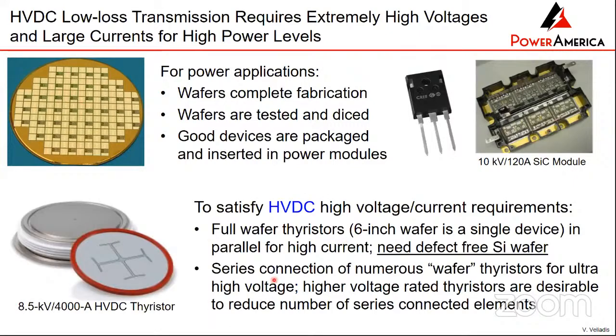And that's what is being done for silicon carbide. However, if you look at silicon, because it's such a good material and the whole wafer is defect-free, they can make a whole wafer as a single device. So in silicon carbide, because it's a newer material, the wafer has defects, and as a result, you cannot use the whole wafer as a single device. In the case of silicon, you can use the whole wafer. So a lot of the work that's being done in silicon carbide is basically to get to the point where the wafer has very few defects, and that's very challenging.